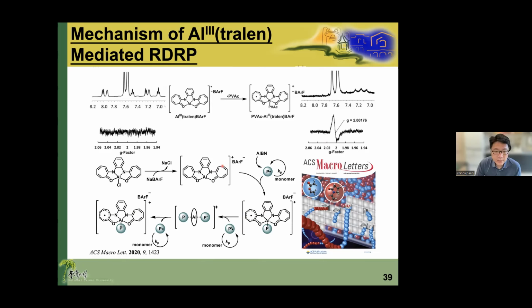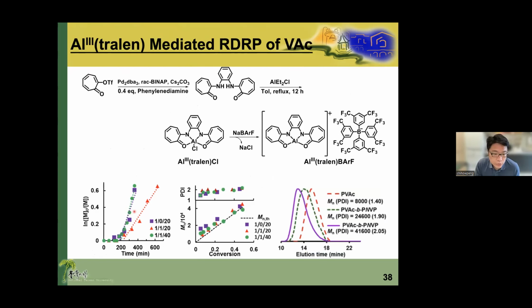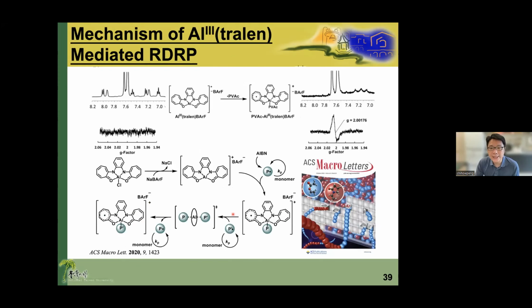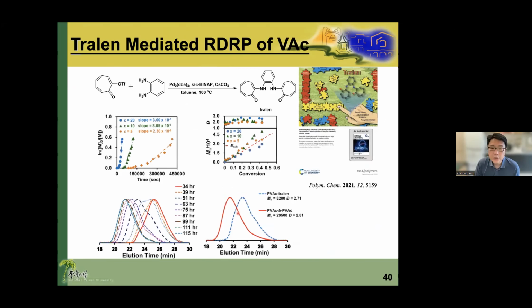But the surprise is always there. So back to this figure, you could find once my student forgot to add this salt to remove the chloride. However, even though he forgot to add this salt to remove the chloride, the polymerization control is okay. So we started to think maybe the aluminum center is not that important, because even when it was fully coordinated, the polymerization still can be controlled. So we tried to use the ligand to mediate the controlled radical polymerization of vinyl acetate, and we surprisingly found it works.